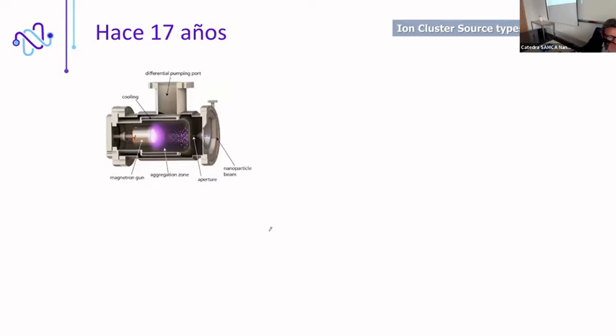So how does it work? This is a cluster source based on a magnetron. You have a magnetron inside a cavity here that is a closed aggregation zone. You extract the atoms from a target using the plasma of the magnetron. If you are lucky and you have a density high enough inside the aggregation zone, the atoms will collide with each other and start to form clusters and eventually nanoparticles. Thanks to differential pumping here, with a venturi type of pumping, we can create a beam that is extracted from the aggregation zone and projected in this direction, where you place the substrate you want to cover with nanoparticles.